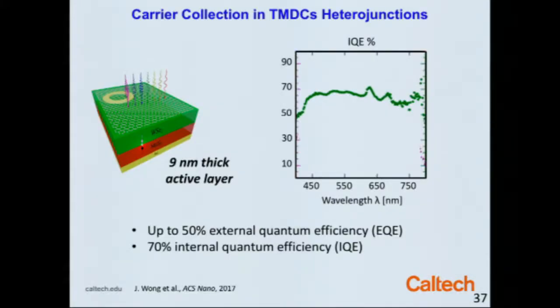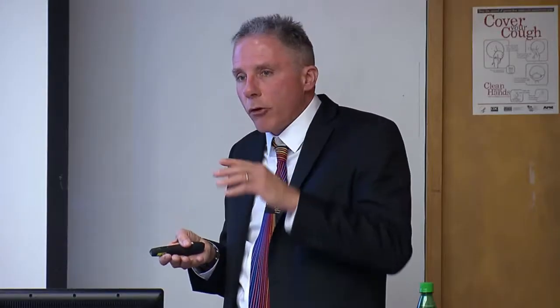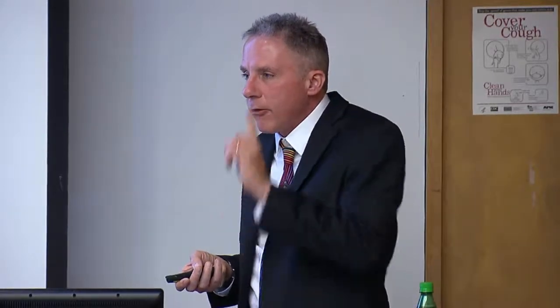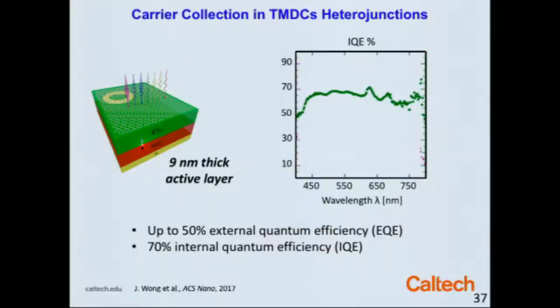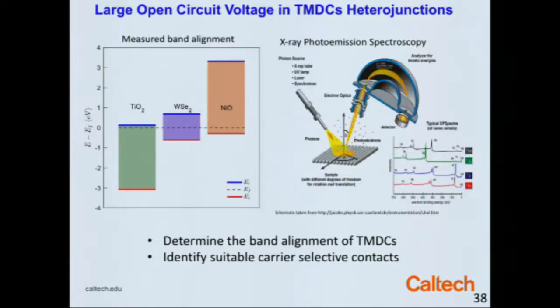When we got into the game, the records were around 15%. So we were able to show that we can not only have high absorption, but high carrier collection. In fact, the reason we have high carrier collection remains very much a mystery to me, because everything we know about the electronic structure of these layered van der Waals materials suggests that you should not have very facile charge transport perpendicular to the planes — you should have high mobility only in plane. So we think this might be defect mediated, but this is an active area of research at the moment.